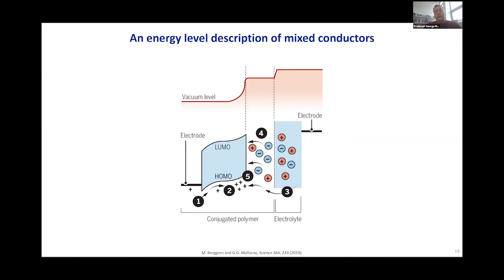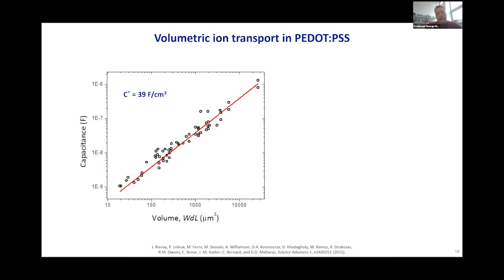We're trying to develop a language, not only to understand how to develop better materials, but also how to describe the properties of these materials by using semiconductor language. So we'll leave it at that and go back to a material which is called PEDOT:PSS, which acts as an ideal volumetric capacitor. So in this material, its capacitance scales with the volume of the film, which means that the thicker you make the film, the higher the coupling between electronics and ionics.